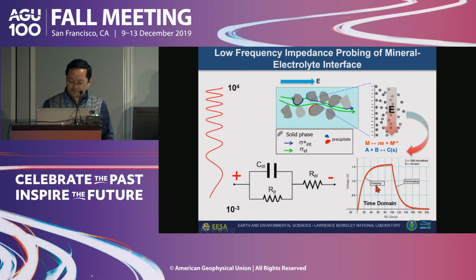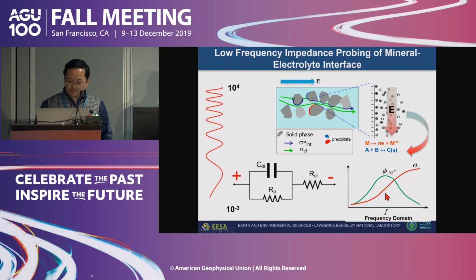In the time domain, you're looking at the charging behavior of the interface. When you turn off the power, you don't have an immediate drop; you have a decay of the electrical conductivity. In the frequency domain, you scan the system through a range of frequencies and get a frequency-dependent conductivity. You also have a phase or imaginary conductivity behavior that shows dispersive behavior, and the magnitude and location of this imaginary component is characteristic of the electrical properties.